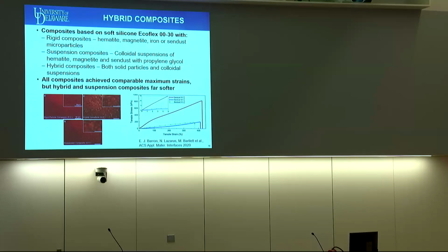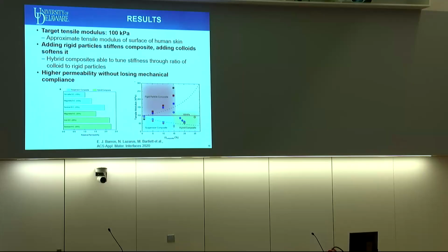And as we'd expect, all three of the composites had very similar maximum strains, again in about the 300 to 400% range. But the rigid particle composite had a significant increase in stiffness. The hybrid and suspension composites remain far, far softer. So we have gained, again, this benefit of being able to reduce the mechanical properties. The target in many of these cases tends to be about 100 kilopascals, which is approximately the stiffness of human skin. So we're often talking wearables, for wearable devices or wearable robotics.